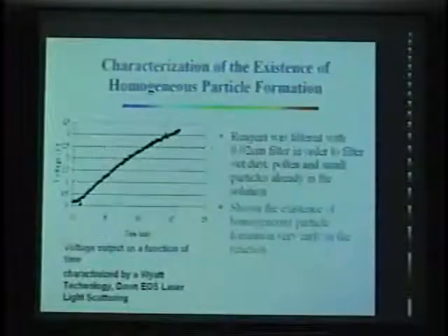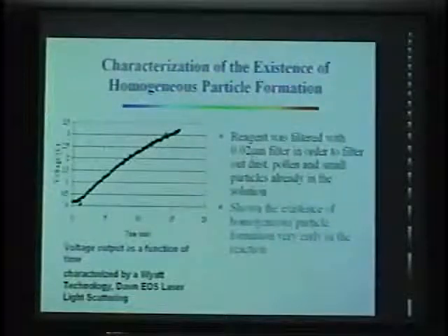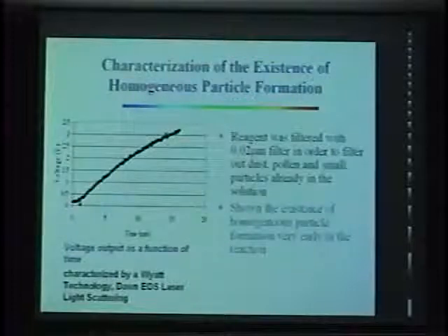Okay. So just to show this, we follow this with dynamic light scattering. We found that once you mix the reactants, within a short time, within minutes, you start to see particle formation. Okay, and that's showing nanoparticles forming in the solutions.